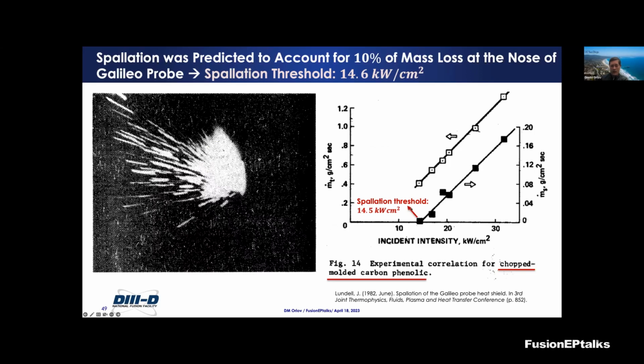Usually this spallation process has some kind of threshold after which it kicks in, but it was estimated that when the Galileo probe went into Jupiter, spallation accounted for about 10% of the mass loss. This is the mass that needs to be sent into space that we're paying for, and that's lost through spallation.